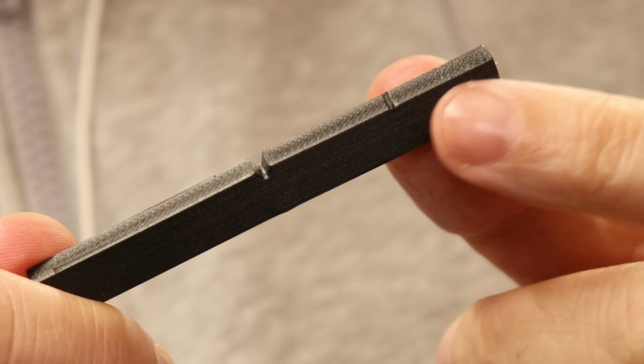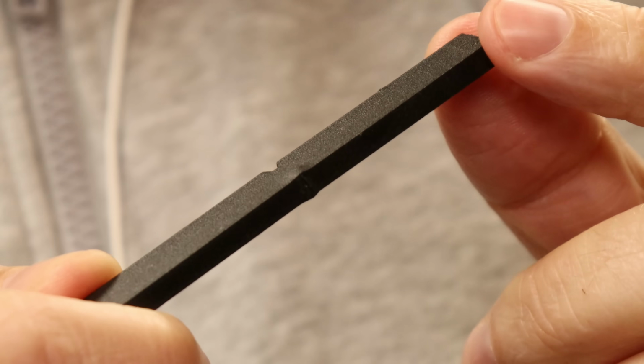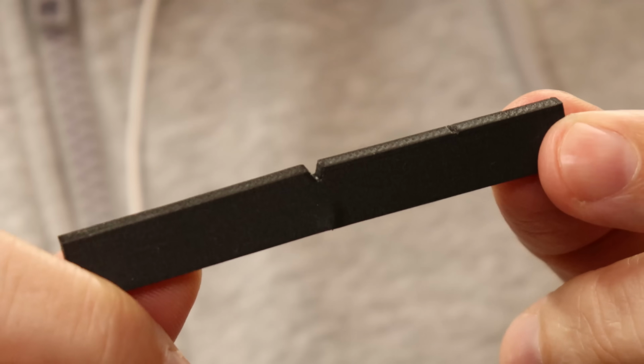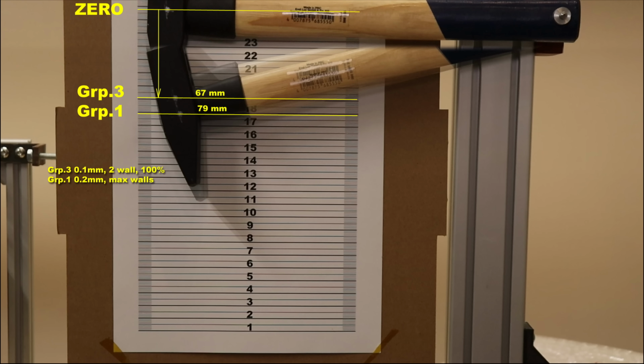That was the impact position of the hammer, and it just started with the bending, but it is still completely solid. I tested really many 3D printed test objects with this machine, but not even one was even close to this state. And between group 1 and 3, well, group 1 is again stronger, tougher material in this case.